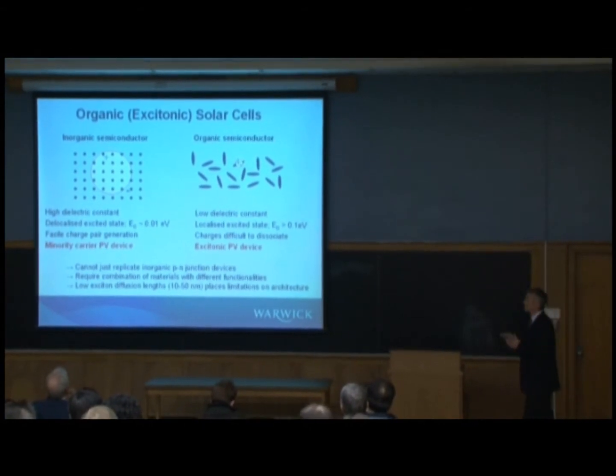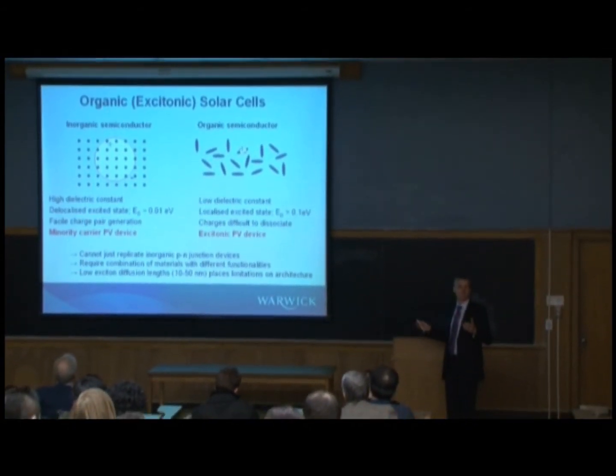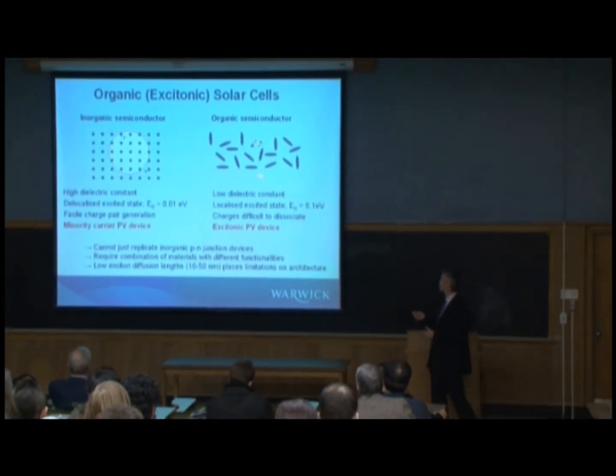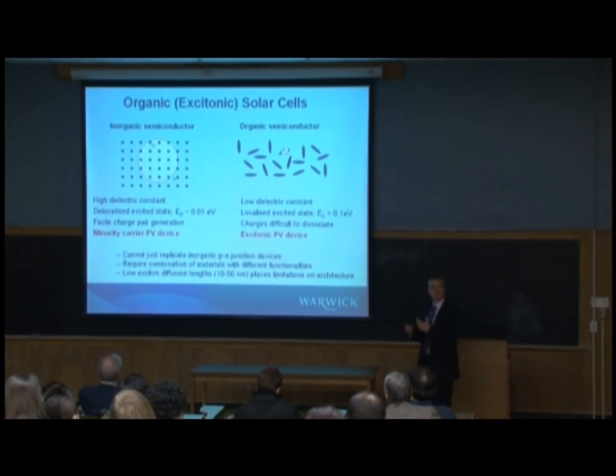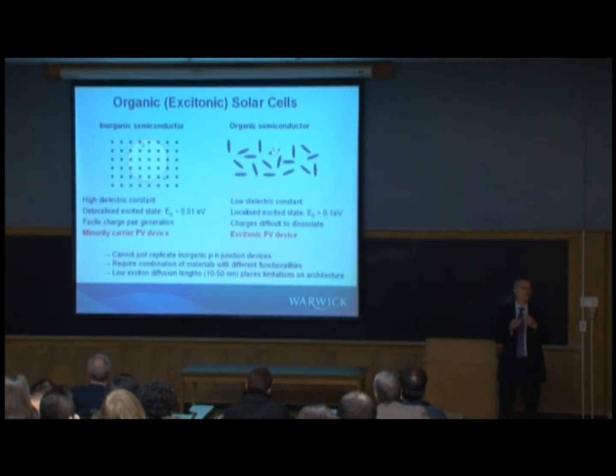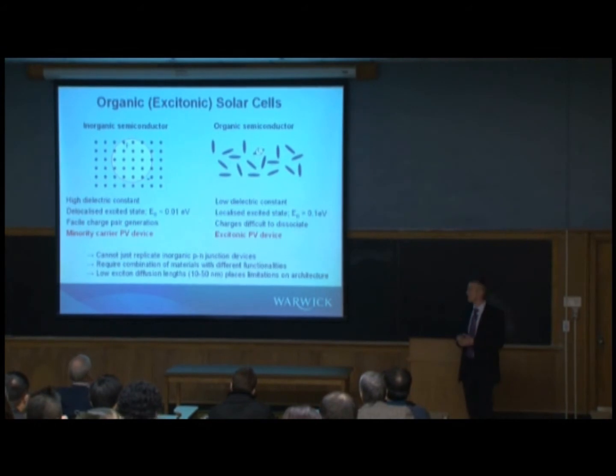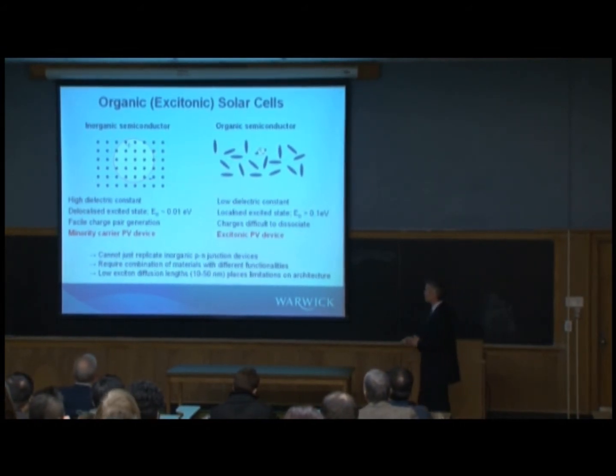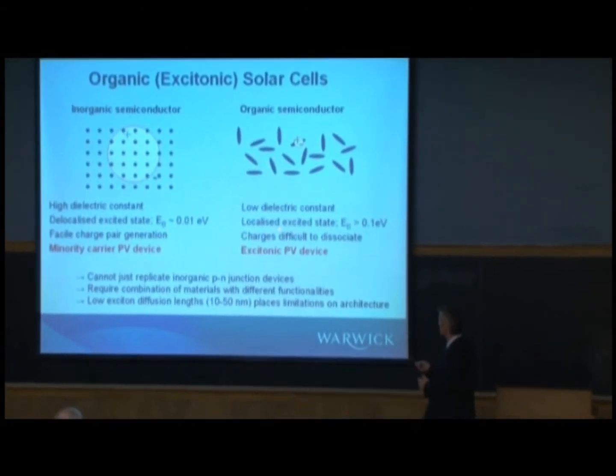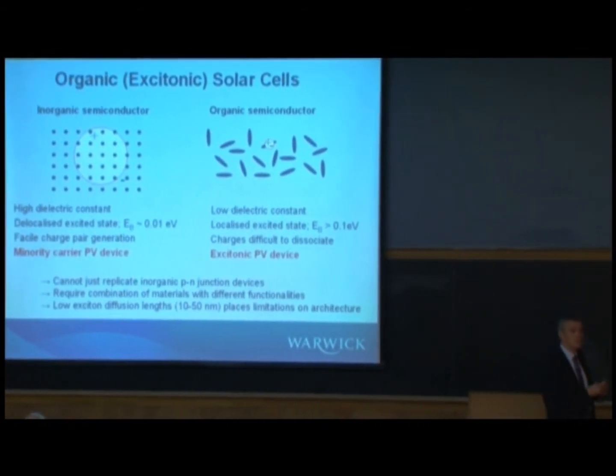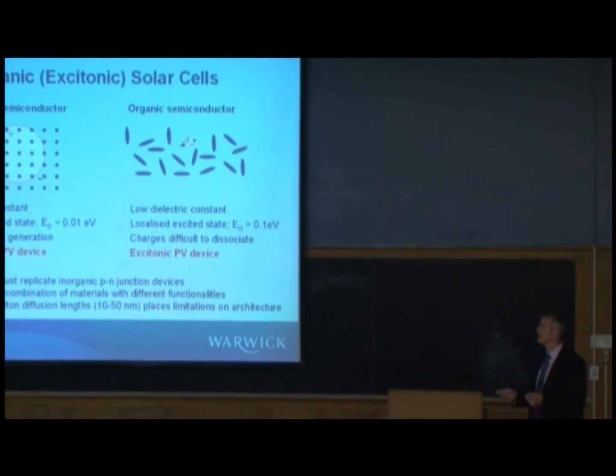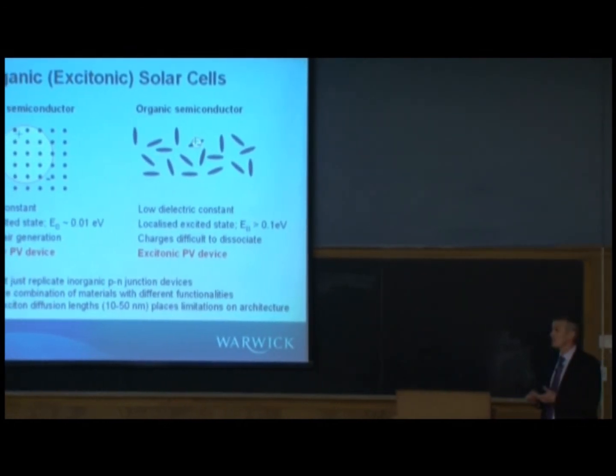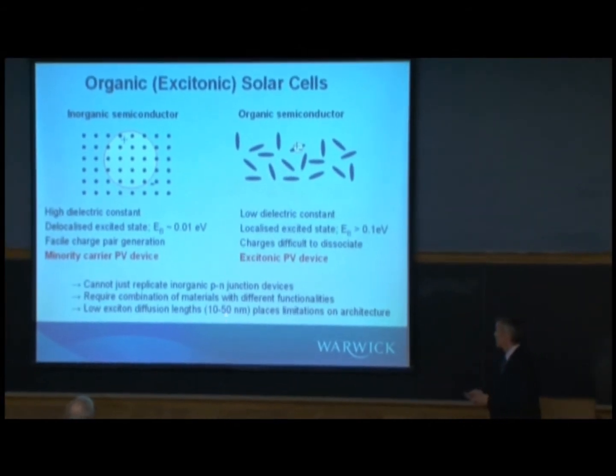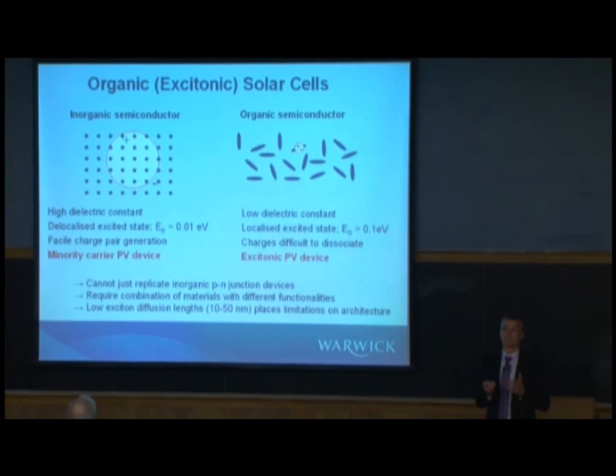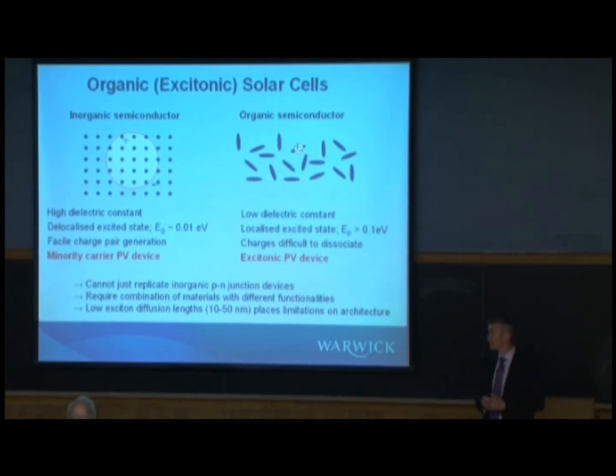And so what you can't do is simply say, well, I'm going to make a PN junction in the same way that you do with silicon. You can't do that with organic or excitonic cells. You have to combine different materials with different energy levels, different functionalities, etc., in order to make a practical device. There's one further point which is important, that this excited state, this exciton that's generated, has a very low diffusion length in organic materials. So if you take a polymer, the diffusion length will just be a few nanometers. You may get up to around 50 nanometers for a reasonably crystalline material, such as pentacene, but it's still very low. And again, that places some constraints on the design of your device.